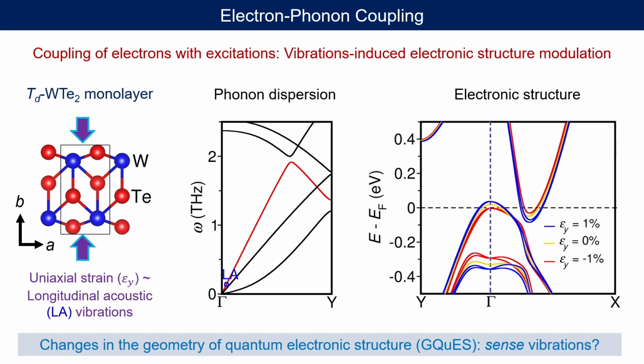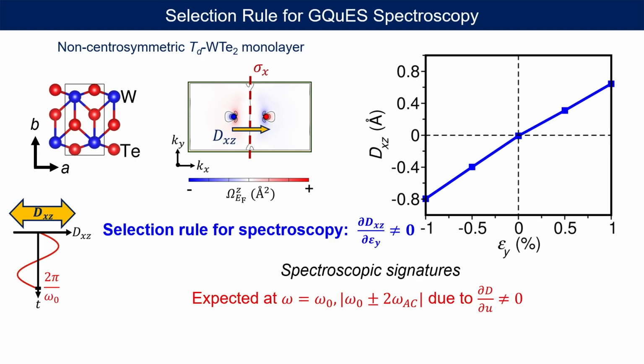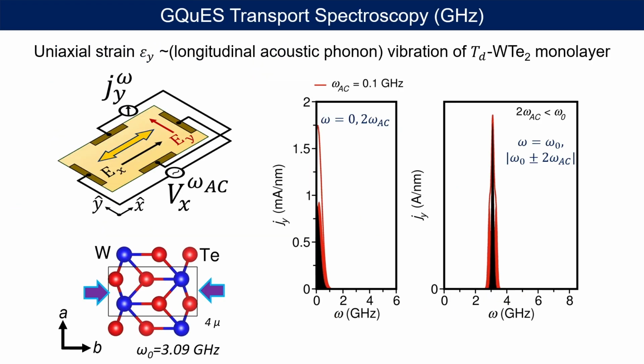And if you look at the electronic structure, the bands will oscillate with respect to this strain 1% and -1%. Indeed, this is to tell you that knowing band structure does not tell you if anything is changing in the quantum geometry of electrons. To know quantum geometry, you have to calculate Berry curvature or Berry curvature dipole, and we explicitly show that it's linearly proportional to the strain that you freeze in the lattice, and as a result, you will see peaks in the Hall signal at basically omega naught and these additional peaks. So this is our specific prediction for tungsten telluride.